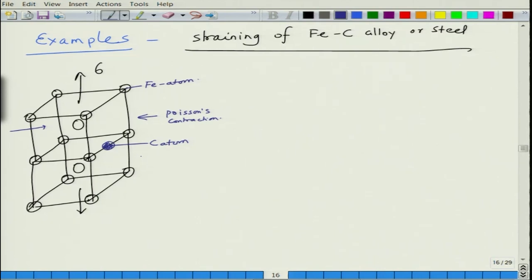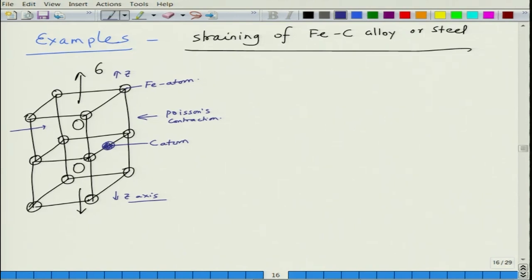If this is the z-axis, you can only elongate along the z-axis. If you are able to move the carbon atom out of the way to another interstitial position along the z-axis, it has space to go to an empty place along z, but at the same time it also allows the other direction to contract. Otherwise it would not happen because the carbon atom is quite large compared to the available space. Essentially this is again a function of loading rate — this carbon atom will have to jump to another interstitial position during straining.